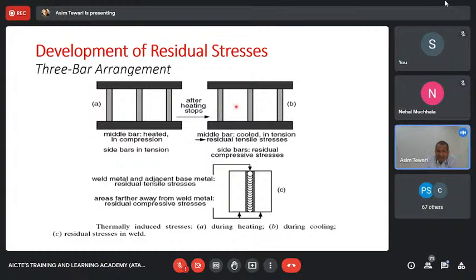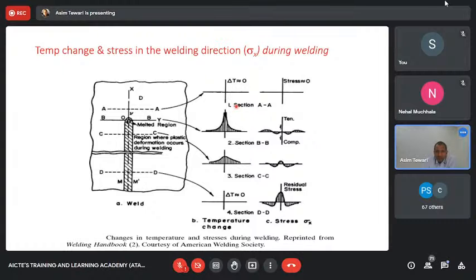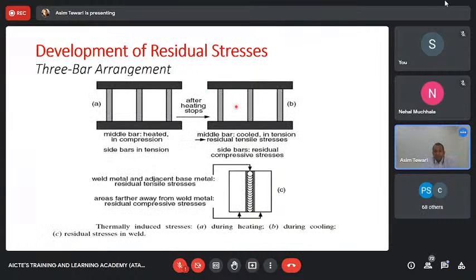Now what happens is, and I'll just show you here, maybe I'll show you in the 3-bar first. So just imagine if you have 3 metallic bars which are joined here and joined here, or welded here, let's say. Now if you start heating the center bar, what would happen? If you take a torch flame and just heat the center bar, the heating of this will make it expand itself. At the same time, the other 2 will also become warm and they'll start expanding, but not to that large extent. Now, this expansion is essentially nothing but an eigenstrain.